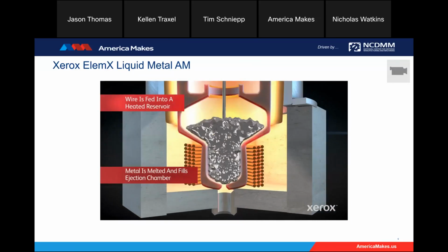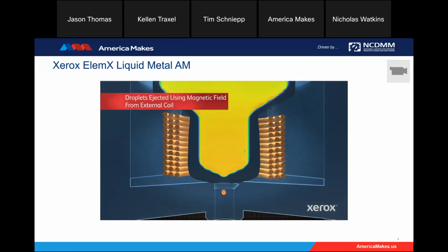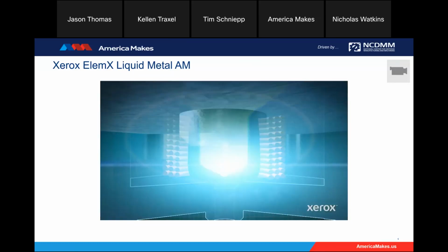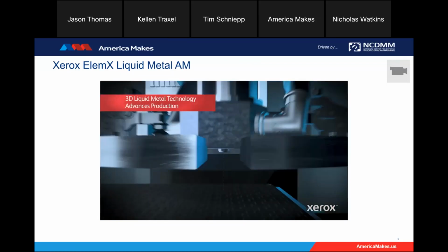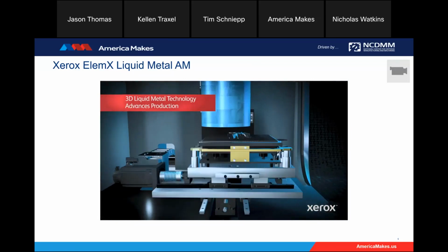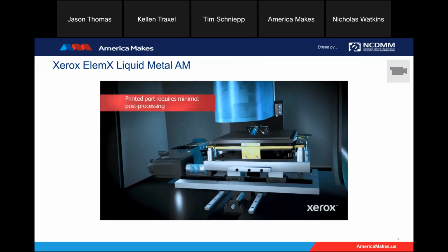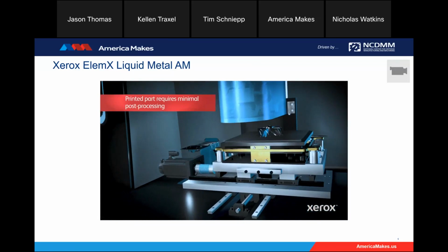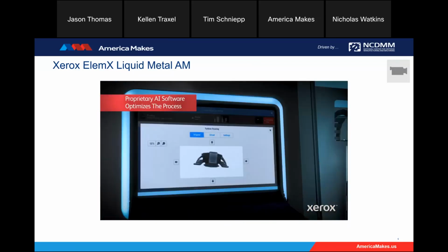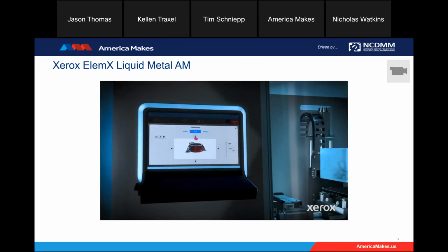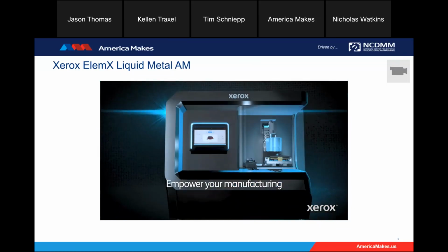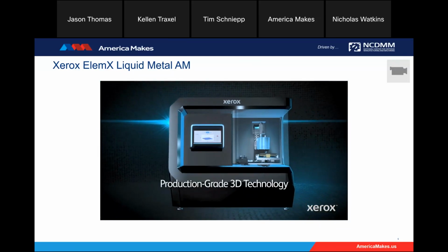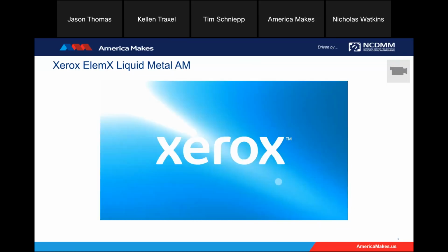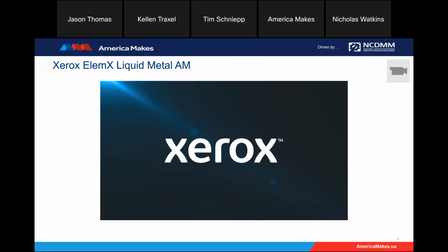We flood that with argon gas that provides a shroud to help control and reduce oxidation. And then there's a set of coils that you see there that we fire continuously at high frequency, and that creates a Lorentz force, which dispenses the droplets onto the heated build plate. As you can see, we move the build plate in the XY direction. The head is kept stationary, though it does go up and down in the Z direction, and we do that to help improve repeatability and give the system additional stability. And then for all industrial controls, we have a partnership with Siemens on the hardware side that leverages their best-in-class controllers and gives us some excellent manufacturing-oriented capabilities.